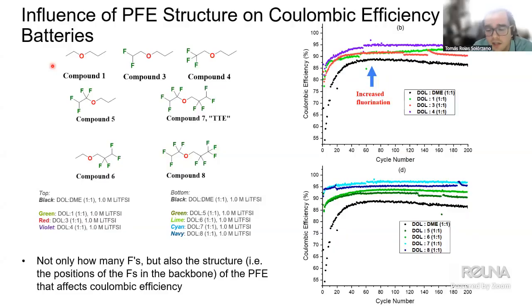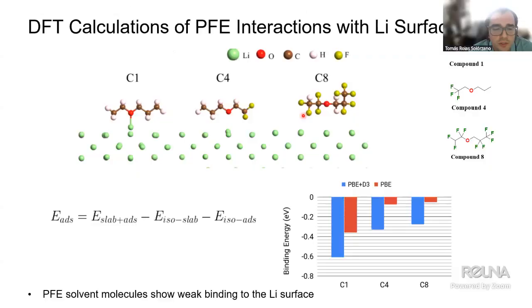These are the experimental results, which gave us an indication that we could be looking at an improvement in performance if we move away from the typical compound, which is the TTE, as we increase its fluorination. So what we start doing is we select 3 of the 8 compounds, the 1, 4, and 8, which have different grades of fluorination, like the typical 4 degrees of fluorination. And we simply place them over a surface and calculate the energy.